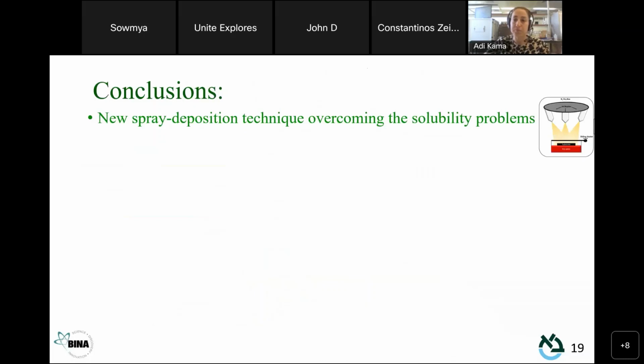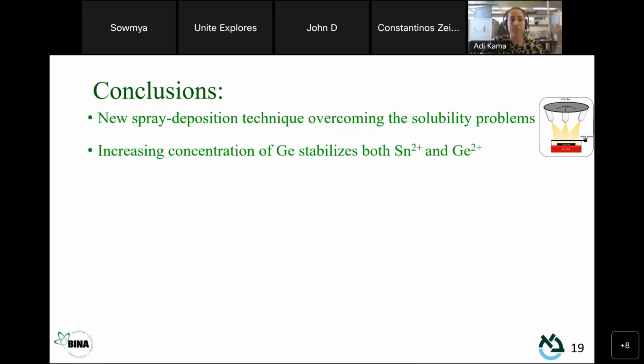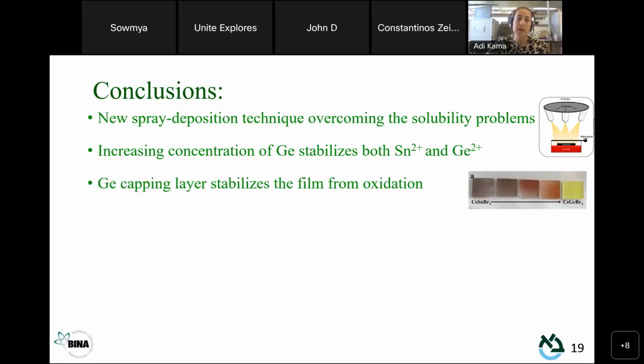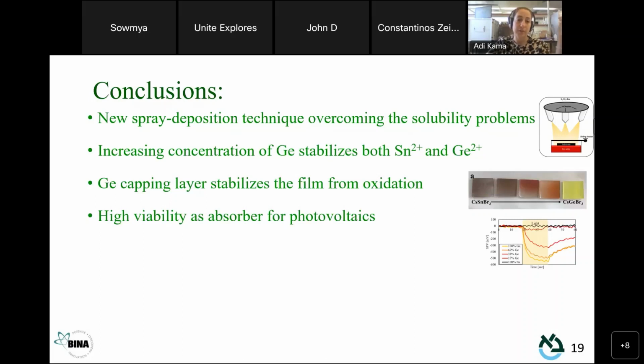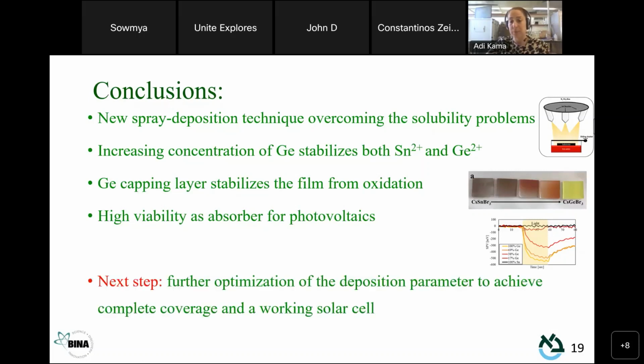So to conclude, I showed you a new spray deposition technique that overcomes the solubility problem of germanium-based precursors. We saw that with increasing concentration of germanium, it stabilizes both the tin 2+ and the germanium 2+. Germanium is forming a capping layer that stabilizes the film and protects it from oxidation. And we have a high viability as absorber material for photovoltaics applications. The next step will be to optimize and to improve the coverage. As I said before, those materials are very new and have very high potential, but need a lot of optimization and further work.